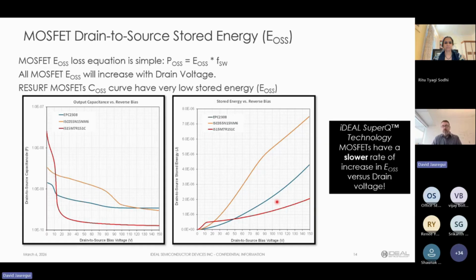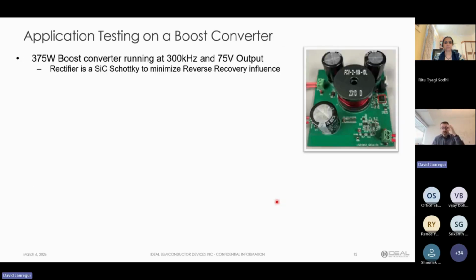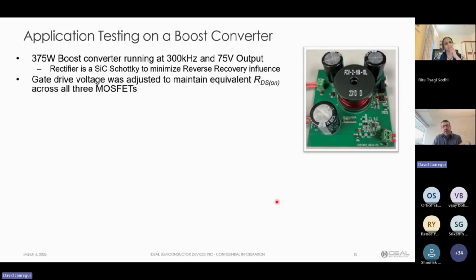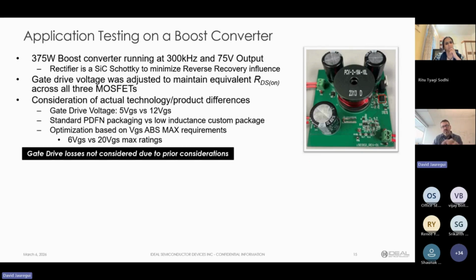And so to put it all together, I have a couple slides that, like I said, are core to the APEC paper that's going to be presented. We took a boost converter at 375 watts, we set the output voltage to 75 volts, running at 300 kilohertz. We put in a silicon carbide Schottky diode. For those of you who know boost converters, there's a rectifier diode on the output. And we intentionally put in a silicon carbide diode, which is over designed, because we didn't want the reverse recovery to become an influence on the operation of the platform. We wanted to normalize everything else and only focus on the MOSFET itself and the switching characteristics of the MOSFET.